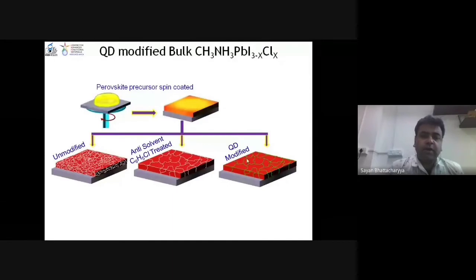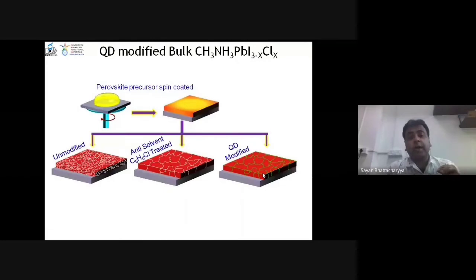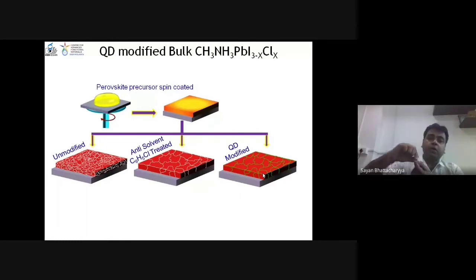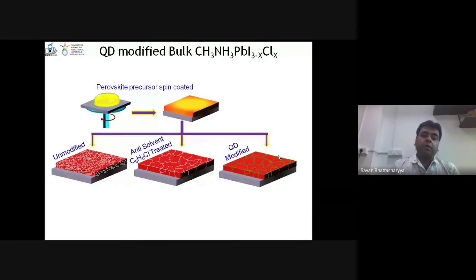So if the surface is too rough, whatever electrons need to be transferred to the electron transporting material like TiO2, titanium dioxide, you cannot extract all the electrons. So you have a lot of recombination pathways. When you excite an electron from the valence to the conduction band, you create this electron-hole pair, which is actually the exciton. This kind of recombination should not take place. You should be able to extract this excited electron away. If you cannot, the electron recombines with the hole and is lost. That is not what we want. The electron needs to be extracted, and roughness creates a lot of trap states, where this recombination happens.